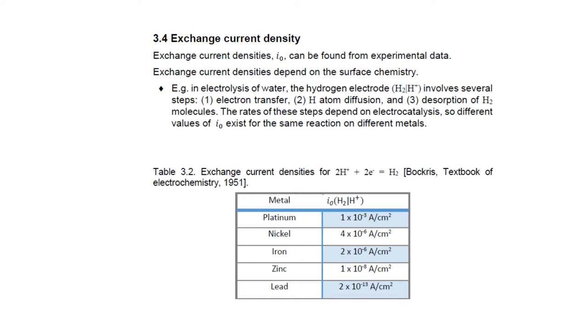In Table 3.2, we see the measured or inferred exchange current densities for the hydrogen cathode on various different metals. So we see that for platinum, a good electrocatalyst, the hydrogen reaction has an extremely high exchange current density. So this is why platinum is used as an electrode in fuel cells, where we want to support, for example, the hydrogen, also the oxygen reaction, to happen as fast as possible.